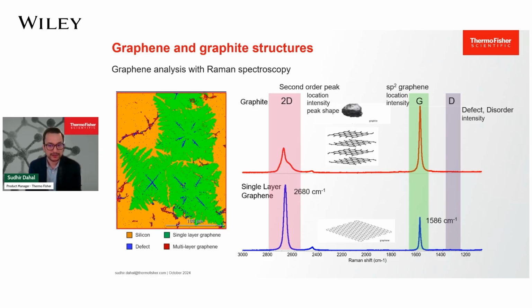As illustrated here in the slide, the G band intensity in the Raman spectrum is higher in graphite compared to graphene. Additionally, the peak shift in the 2D band can indicate the number of graphene layers present in the graphite. Therefore, by analyzing the 2D band itself, it is possible to determine the number of graphene layers in a graphite sample, all using Raman spectroscopy.